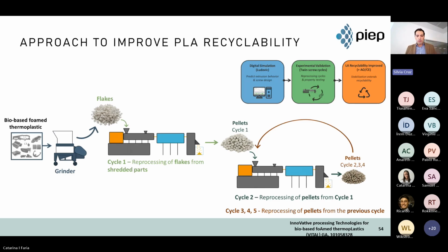Schematically, how do we run that? We get final parts from the trials, from developments and from the industrial trials. So we get bio-based foamed thermoplastic parts. We pass them through a grinder, and we get the flakes. And then we immediately run the flakes through a twin screw extruder to make the first cycle of degradation, of reprocessing. After that, we get the granules, and then we reprocess again 100% in the extruder. So with this approach, we get a fast degradation of the material. The idea was then to characterize and evaluate what was happening with the material and how we can at least avoid or limit the degradation of these materials.